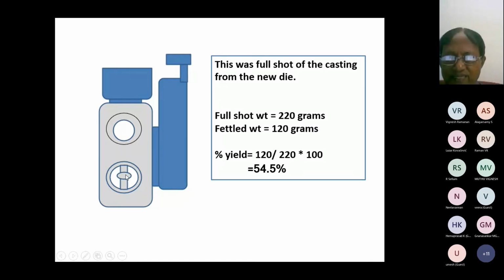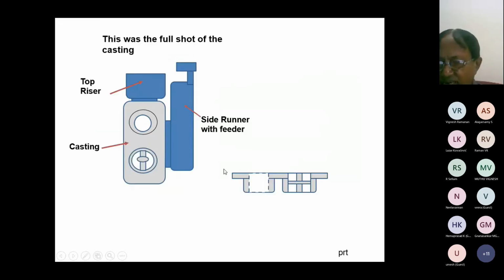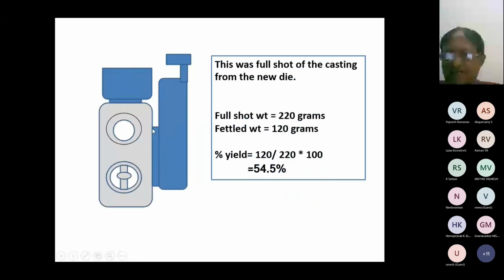Some shrinkage came because this boss is isolated. Because this is a different one from these bosses. What we did, this is the core, we put some long copper chills with the air vents at both the ends. This is a long one. And this copper chill and the air vent solved the problem very well. This is not much of a problem because this is nearer to the top risers. And this was a great success for us.